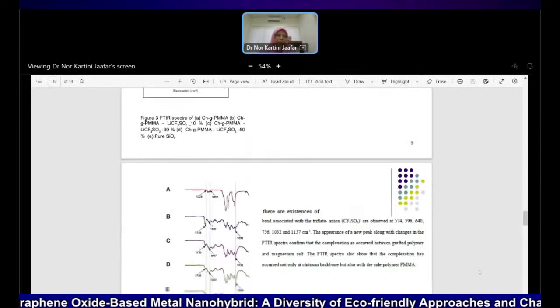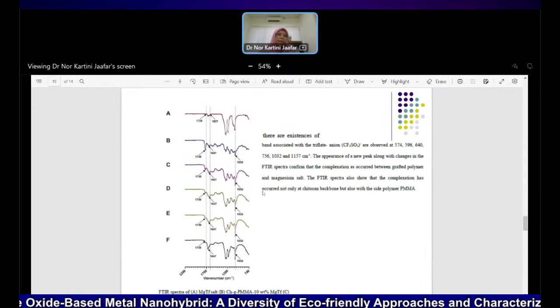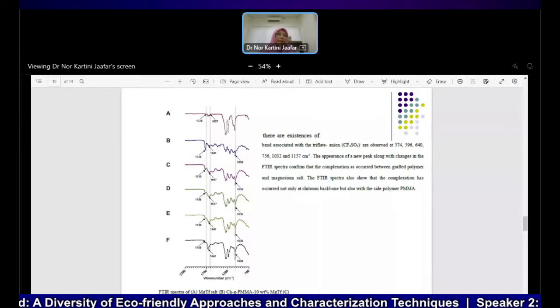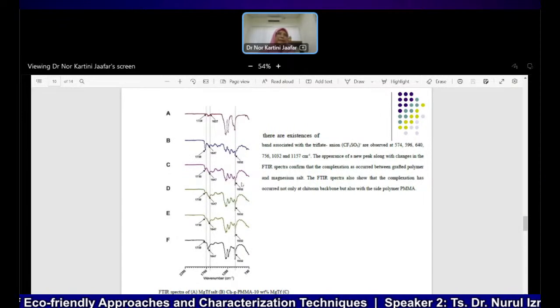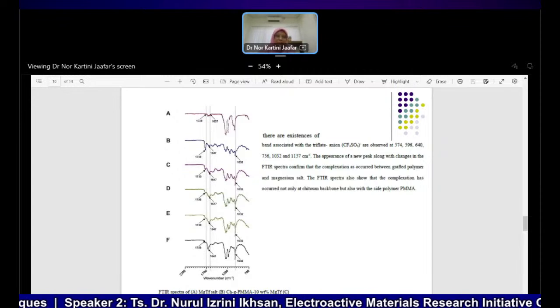Also same with the magnesium, we can also see in the blend, the chitosan blend polymer grafted with magnesium - I can see the existing peak of magnesium triflate within the spectrum of the blend. So we assume complexation between the grafted polymer and the salt occurs.